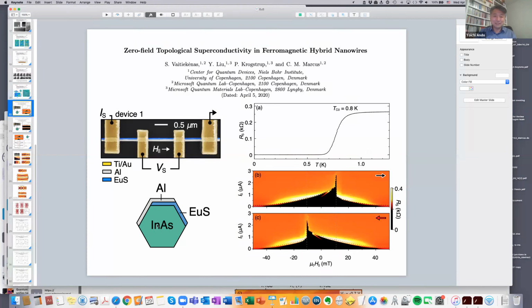Yeah, I have just one question. In the introduction, you suggested that the unsmooth nature of the interface between europium sulfide and aluminum has something to do with the data that you're going to show. Yes. But this was actually never presented. So I didn't really say it. You're right. So let me say what I think was necessary. I think that there are two features where that roughness plays a role. One is that I think that if the roughness scale is small compared to the coherence length, it looks like spin flip scattering. That at zero external field, there's a little bit of domain structure left. I mean, it's mostly magnetized, but we know that it's not fully magnetized. So from the superconductor's point of view, it sees that as a slightly inhomogeneous magnetic field because of the roughness and also because of the domain structure on a scale small compared to the coherence length.